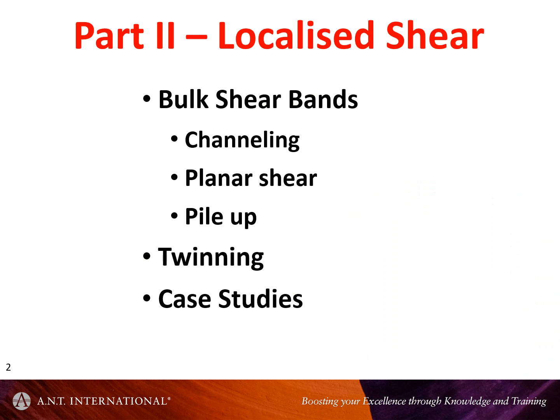Okay, so I've given you an example about localized deformation on a macroscopic scale caused by variations in texture. Basically, a seam welded tube, that was where it's welded. Where the weld structure is anisotropic, it will tend to fail in the weld simply because of the biaxial stress conditions, but that doesn't happen for a tensile specimen.